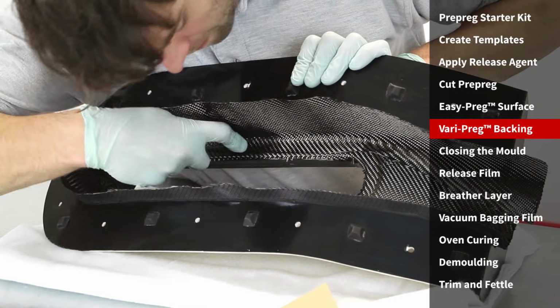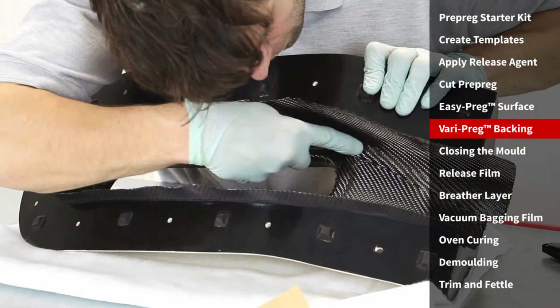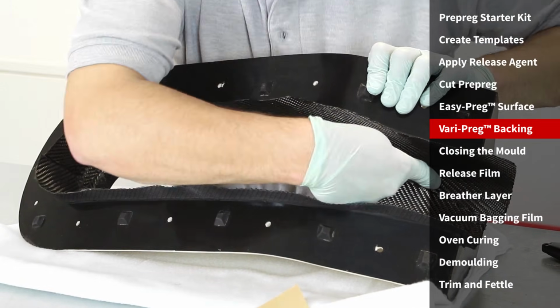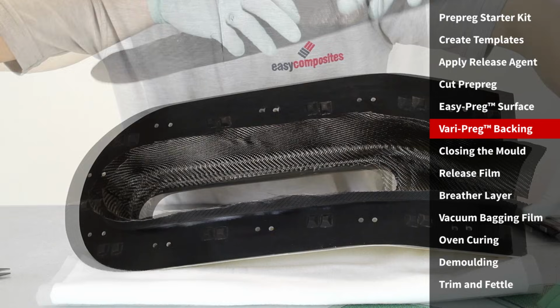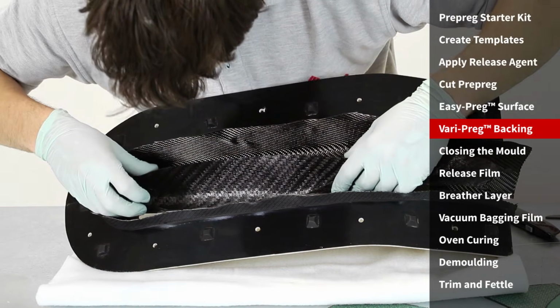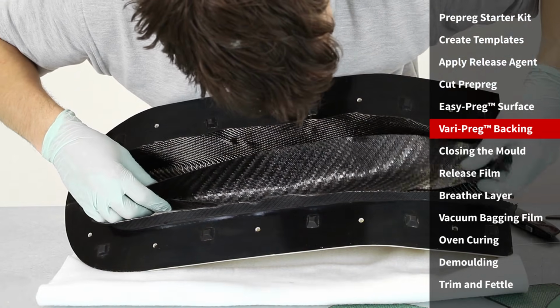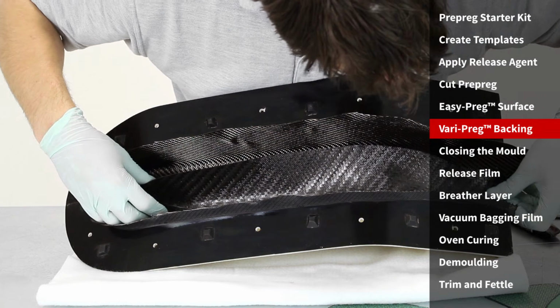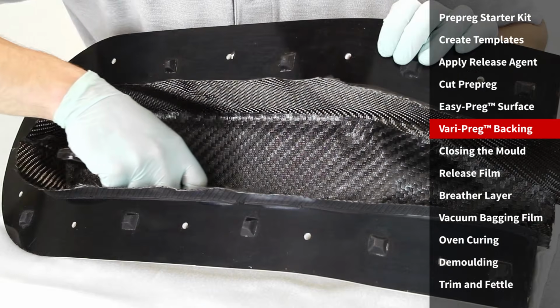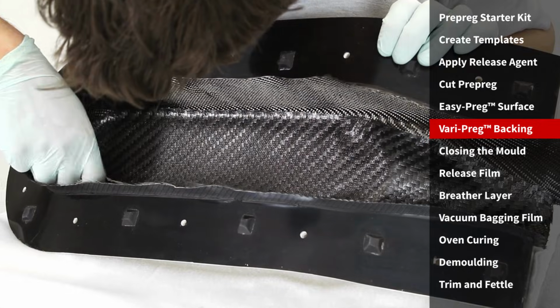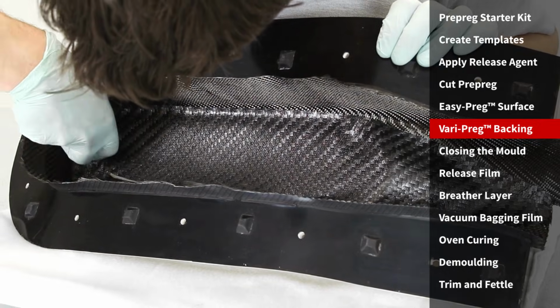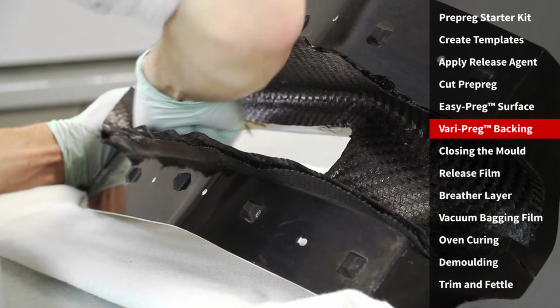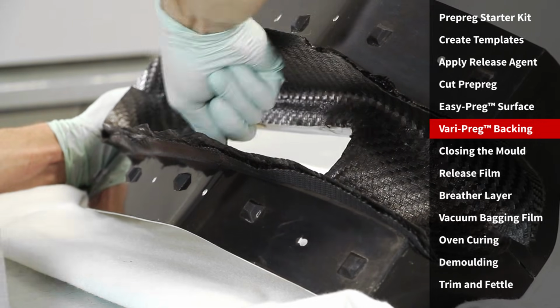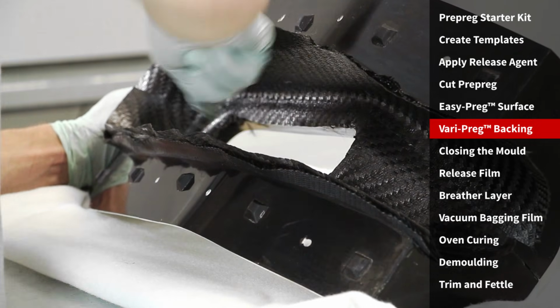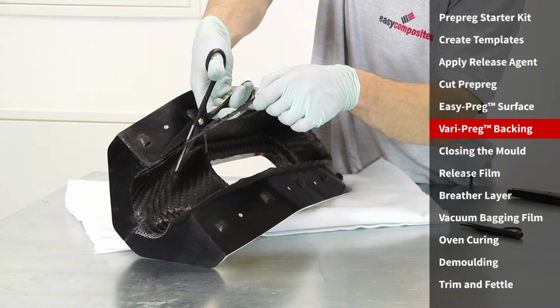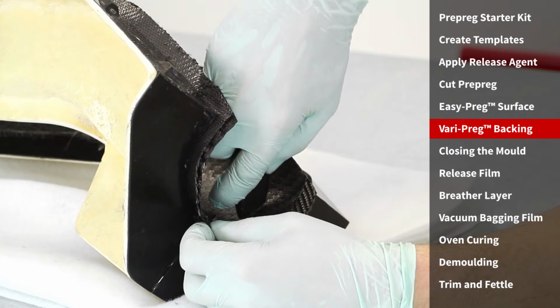A real benefit of working with Pre-pregs is the way that intricate layups, like this, can be carefully assembled step by step, with the Pre-preg tacking itself into place on the mould surface and staying in position. Again, the backing layer we're laying down here is tacky enough to stick nicely to the surface layer. We position it carefully and then apply pressure to stick it down firmly. Excess reinforcement is easy to trim away using scissors or a knife.